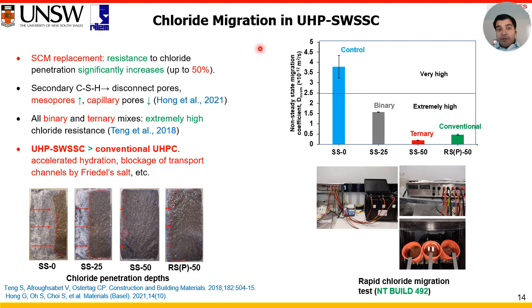Now, an important part for a marine concrete will be the chloride migration into it, and we found that the utilization of slag and silica fume in the ternary marine UHPC significantly improves the chloride penetration resistance. When compared to conventional UHPC, the chloride penetration resistance of marine UHPC is much higher.